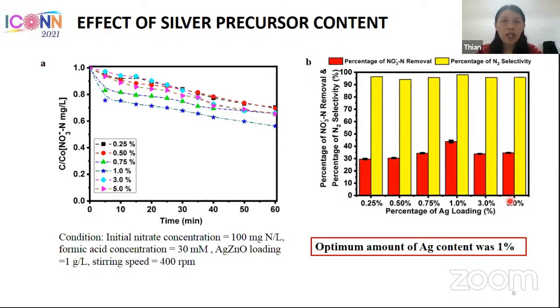So silver acts as an electron sink. It actually traps the electron, which enables a better charge separation. So that is why if we keep on increasing silver content, initially it also increases the percentage of nitrate removal. But beyond 1%, if we further increase the amount of silver in the photocatalyst, it so happens that the silver tends to form clusters. So hence that cluster itself becomes a recombination center. So the optimal amount here is a silver content of 1%.